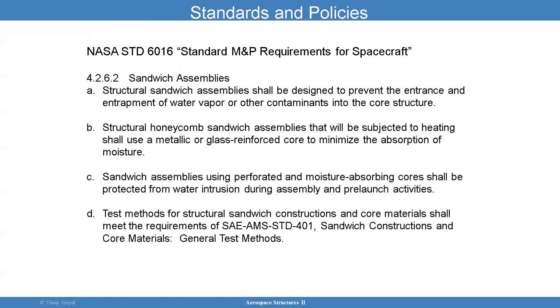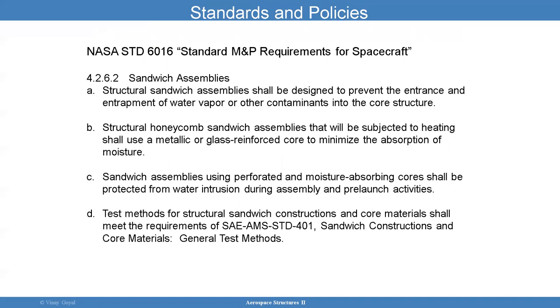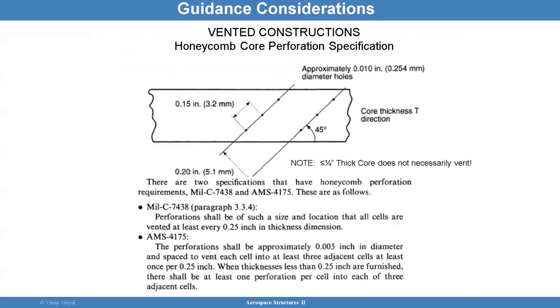NASA Standard 6016 says structural sandwich assemblies shall be designed to prevent the entrance and entrapment of air, water vapor, or other contaminants into the core structure — meaning they probably want it unvented, not vented. That standard also states that honeycomb sandwich structures subjected to heating shall use metallic or glass-reinforced core to minimize absorption of moisture, and sandwich assemblies using perforated and moisture-absorbing cores shall be protected from water intrusion during assembly.